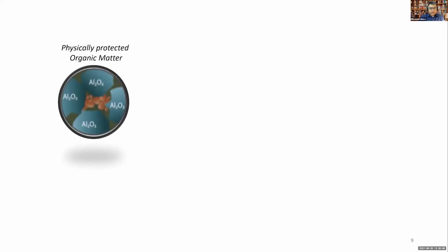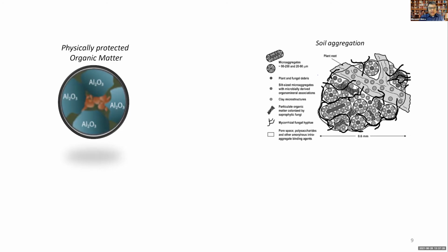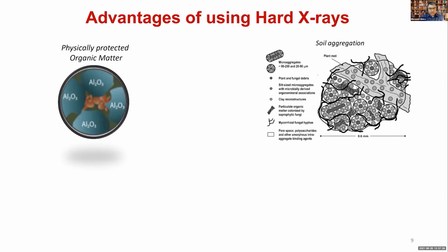But let me prove my point by giving you an extreme example where there is physically protected organic matter in a given sample. There's no way soft X-rays can actually reach this organic matter, because one has to probe through the physical protection of, let's say, mineral before we can excite the carbon, for example, in this case. The reason is that for carbon, which is what I'm going to talk about mainly, the excitation energy is only 280 or 290 eV, which is really low energy, and the penetration depth is much lower. Similarly, if one wants to understand the carbon inside a soil aggregate, there's no way of doing that because of the limitations of penetration depth.